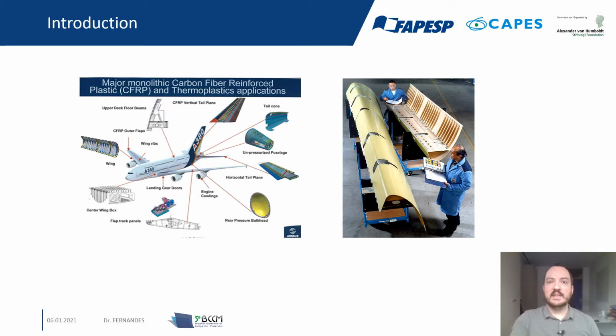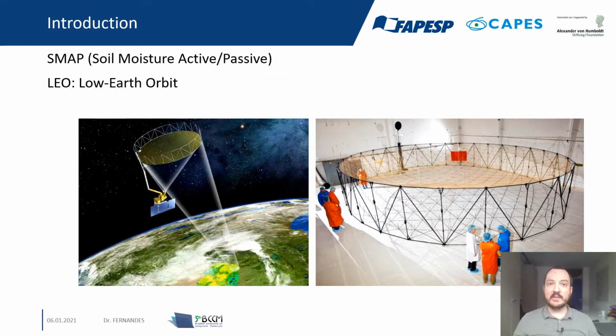Here I emphasize a part in the wing which has a complex shape structure, and in cruising altitudes operates under very low temperature, typically -60 degrees, and is subject to impact events that lead to the so-called barely visible impact damages, which cause significant degradation of the mechanical properties of the aeronautic structure that's made of composite laminates, compromising the airworthiness of the vehicle, despite only a small indication on the external surface of the component. In the aerospace industry, the use of composite materials is also present.